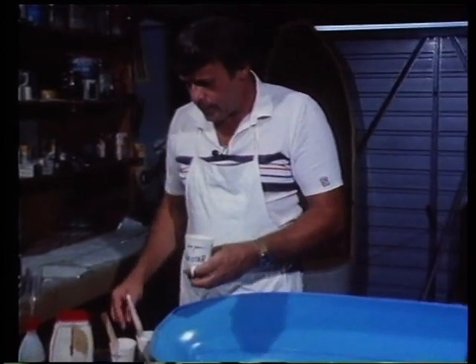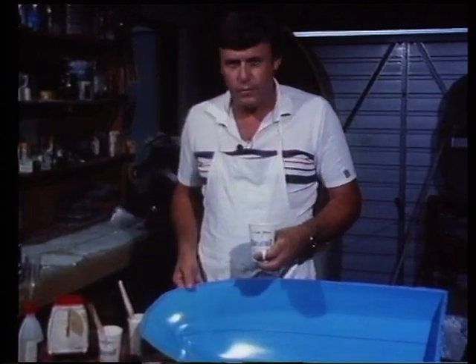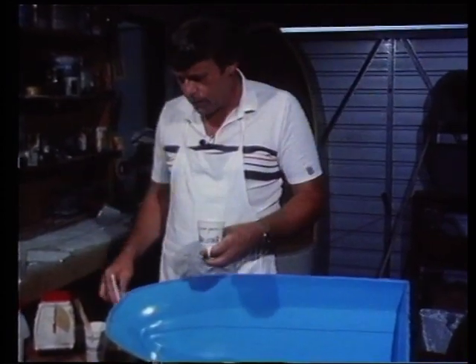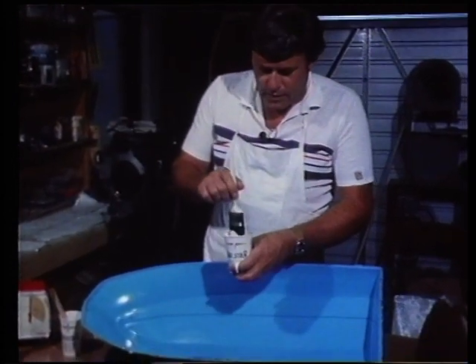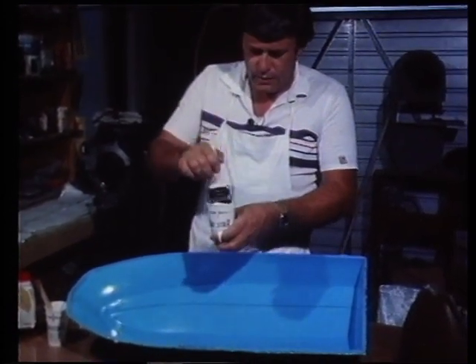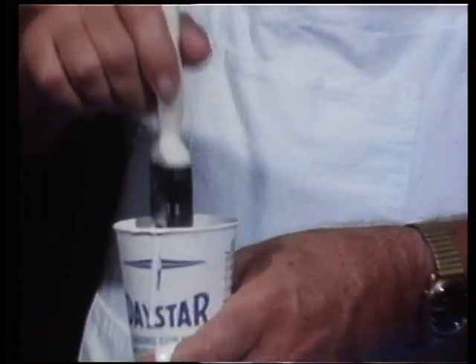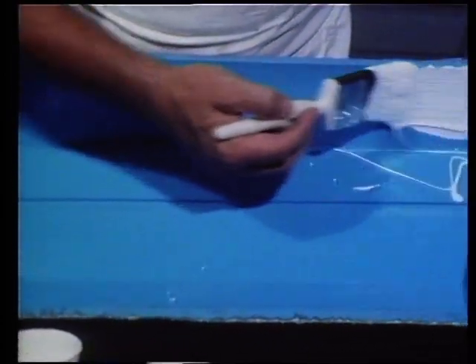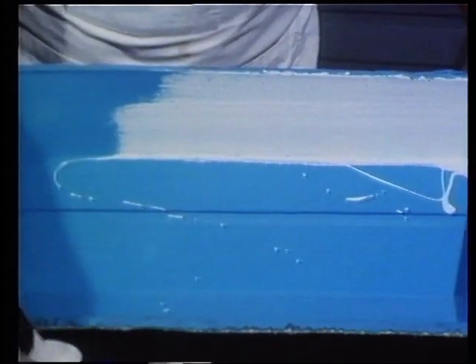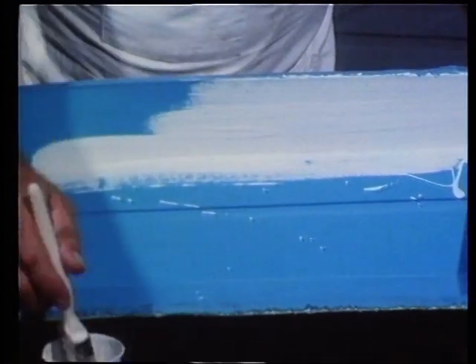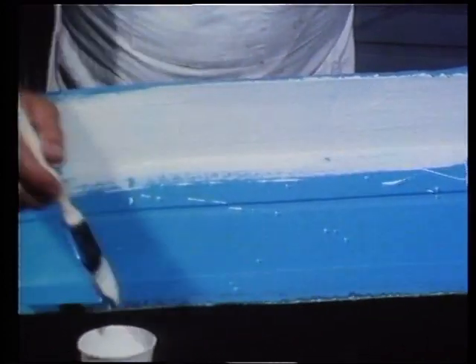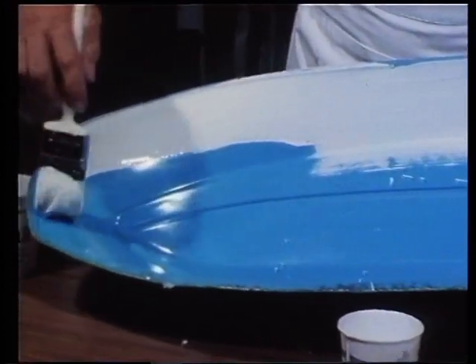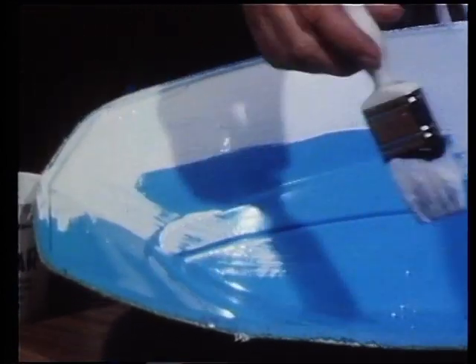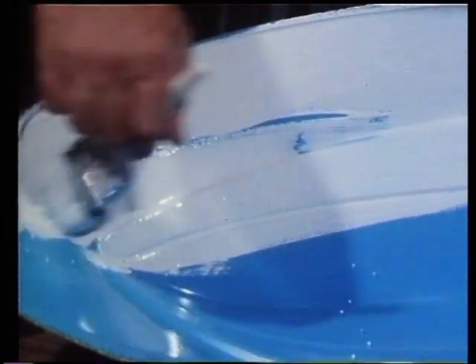Put the stirring stick in another container, and by the way, it's essential to work clean with fiberglass. You must have a container for everything and somewhere to put everything that you use. Now I dip the brush into that gel coat and really load it up. You can see that I've spread the bristles of the brush by bobbing it up and down into the cup, and then I use the brush not to paint it on, but to spread it onto the inside of the mould. I make sure that I have a liberal coating of gel coat on the inside of the mould. In fact, the manufacturers tell us that you should have about 15 thou, again a mix of imperial and metric, but you should have about 15 thousandths of an inch of gel coat all over the surface of that mould in order for the gel coat to do its job.